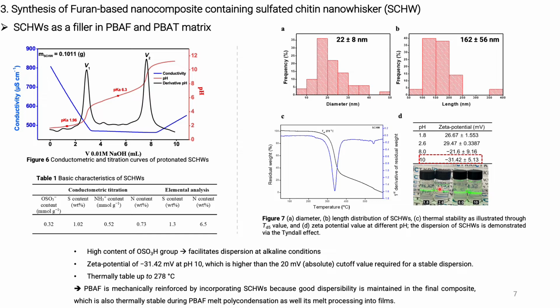More evidence for the good dispersibility of SCHW can be seen through its zeta potential of minus 31.42. This value is much higher than the cutoff value required for a stable dispersion. Moreover, the 5% weight loss temperature was determined to be 278 degrees. Those results suggest that PBAF can be mechanically reinforced by incorporating SCHW because of good dispersibility. Because the good dispersibility of SCHW can be maintained in the final composites, which is also thermally stable during PBAF melt polycondensation, as well as its melt processing into films.